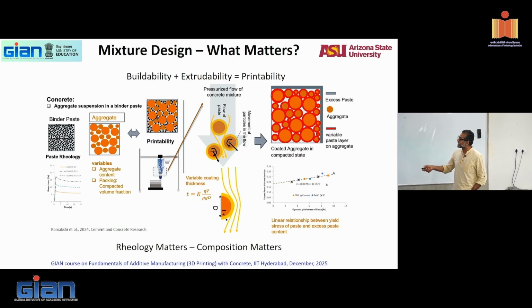You need the paste to have the ideal yield stress and plastic viscosity. You need the aggregates, if you are having aggregates, to be spaced and particles to be packed in such a fashion that you give stiffness to the system, and then you should be able to print it, and then you should be able to build it up well.